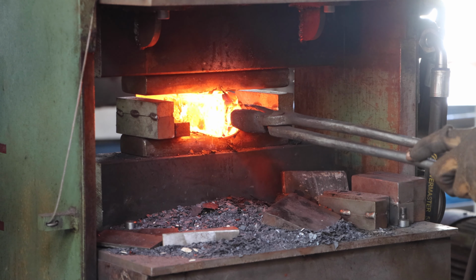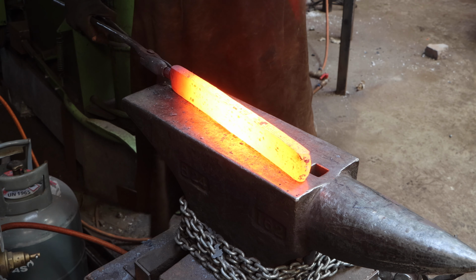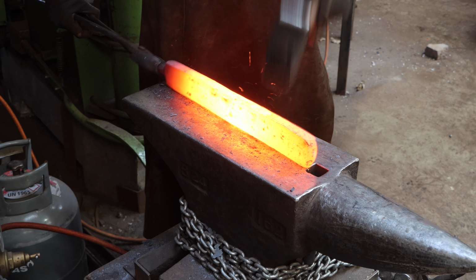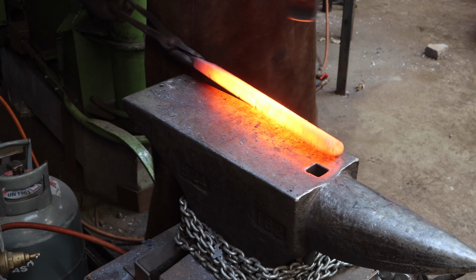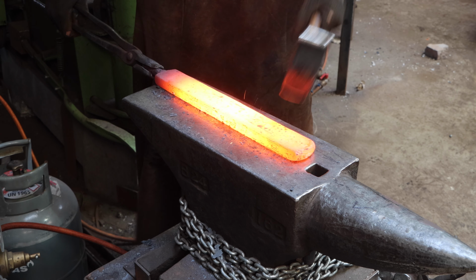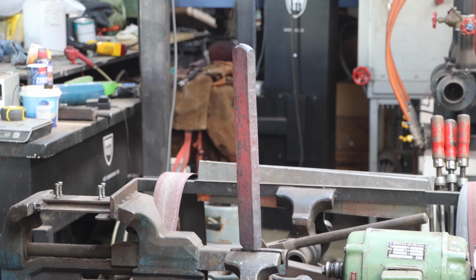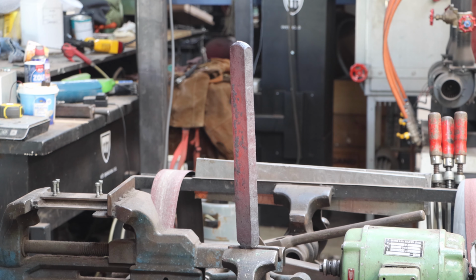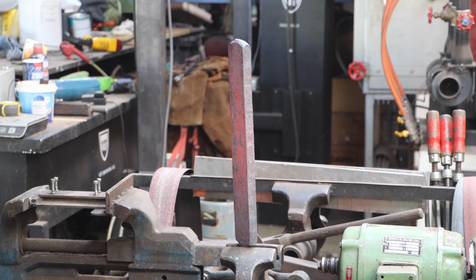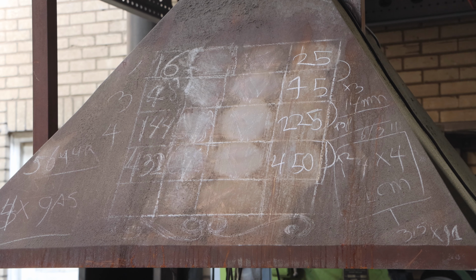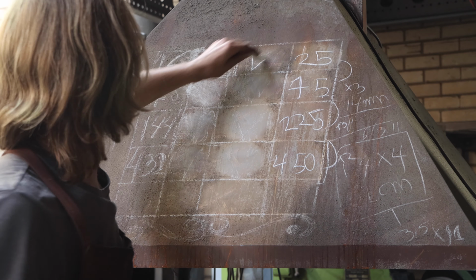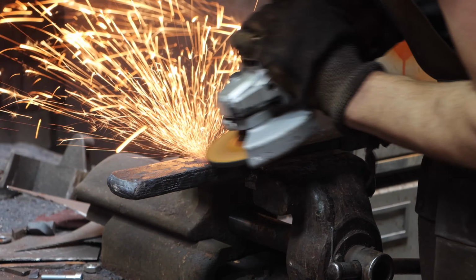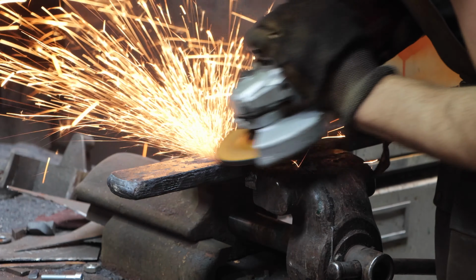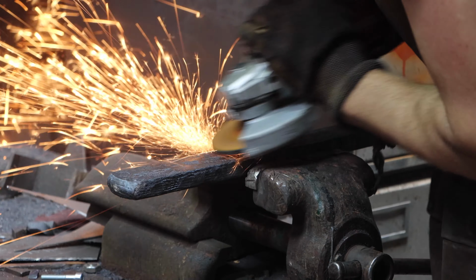For this sword I am making pattern welded layered steel. Two steels are used to create a good contrast. One is 1075 and one is 15N20 steel. One of the steels contains nickel, making it harder to corrode in the acid, creating a good pattern. I forge weld the billet 4 times, stacking and welding it over and over again.